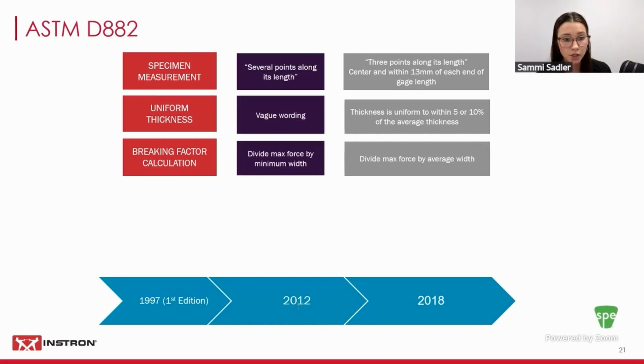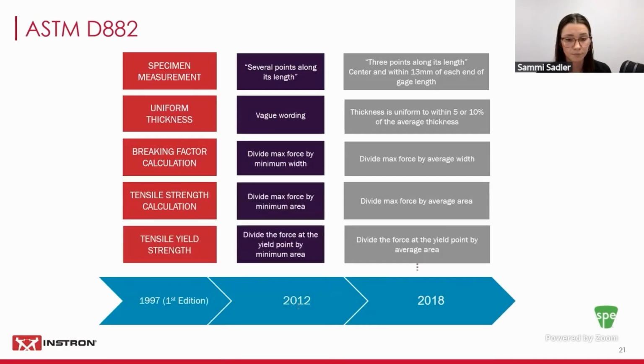And then in subsection 12.2, this was added to the 2018 update, which revised using an average width of the specimen as opposed to the minimum, to stay consistent with how stress and modulus are calculated. And then lastly, subsections 12.3 and 12.6 were also revised: the tensile strength and the tensile yield calculation now use the original average cross-sectional area as opposed to the original minimum cross-sectional area, to stay consistent with how the modulus calculation is calculated.